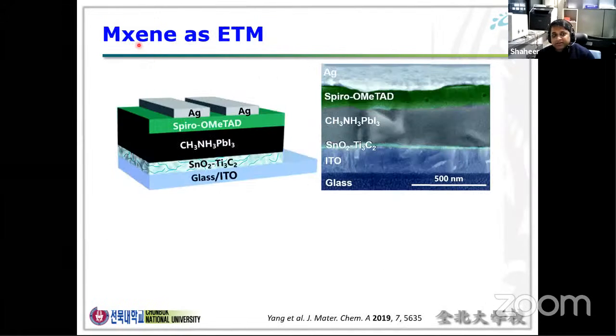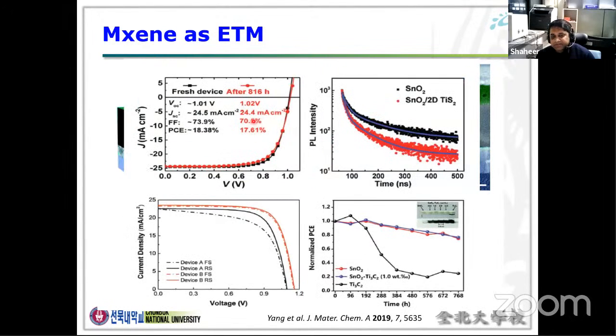Here is an example: in 2019, one group used MXene as an electron transporting layer. They mixed MXene, titanium carbide, with tin oxide, making a very thin layer, less than 50 nanometers. That is enough for the perovskite material. When they checked the performance, the efficiency was over 18%. The stability was also much improved, with only around 8 to 10% efficiency decrease after 700 hours of operation.